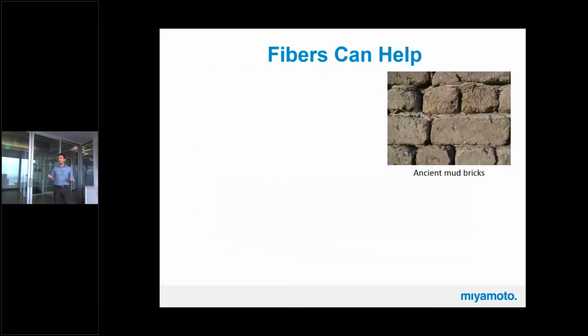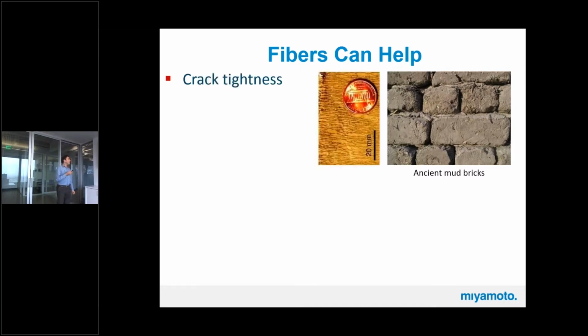So fibers can help. Using fiber in concrete is not a new concept. Ancient cultures used it in mud bricks to control cracks. Mud, they didn't have concrete at that time. Okay, and what do fibers do? Fibers first control the crack width in the concrete. It limits the crack width. And if this is a special type of fiber reinforced concrete, you can see it can generate thousands of cracks, and it's good for the permeability of the structure.